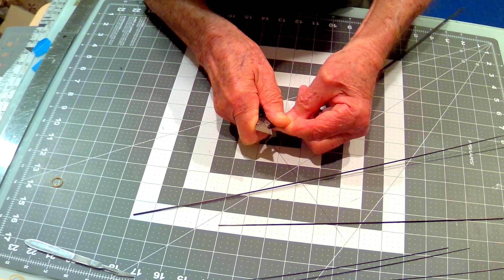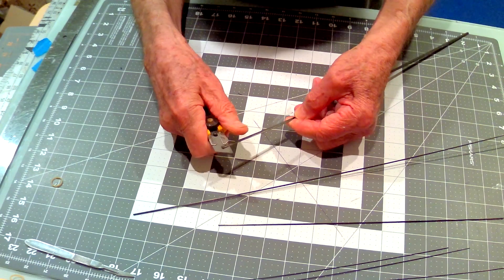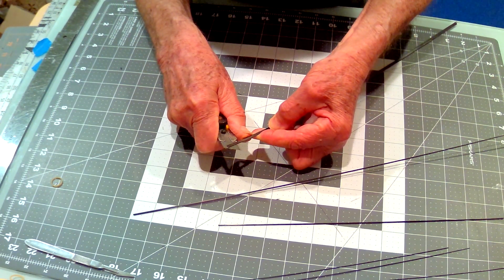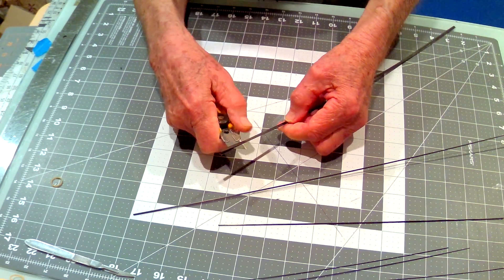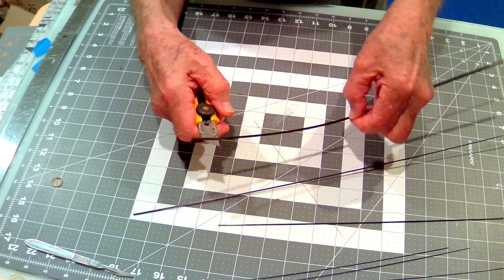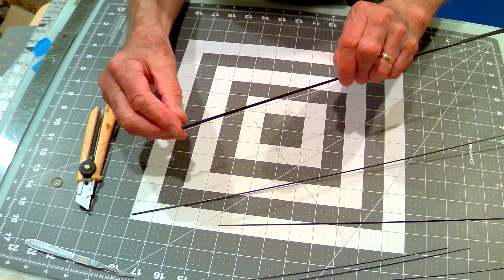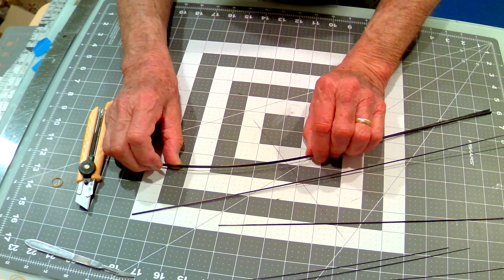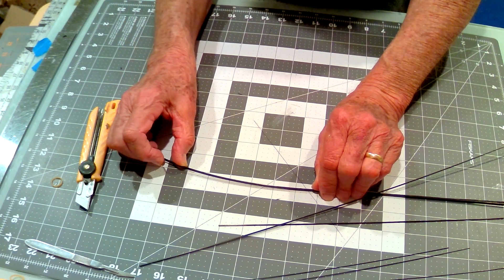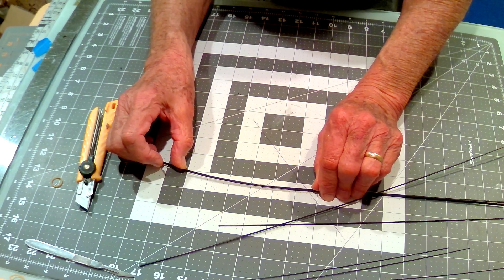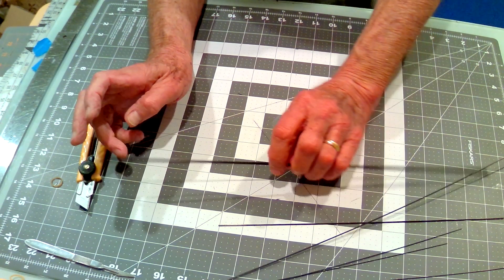I would split it the distance that I want the bend in my spine to be. That can be anywhere from a short distance at the nose to half the spine for a very gradual bend. You split it, super glue it, and clamp it to a form to take the shape you want. When you do that, make the curve slightly more severe than what you want because it will straighten out a little after the glue dries and you remove the form.